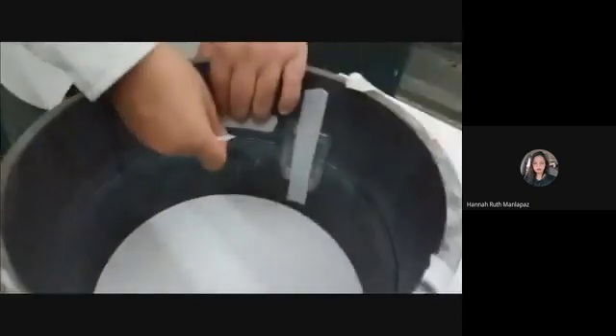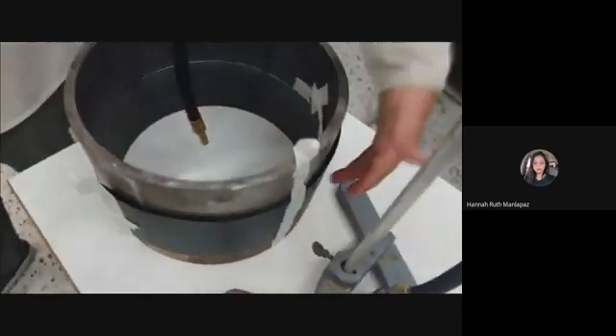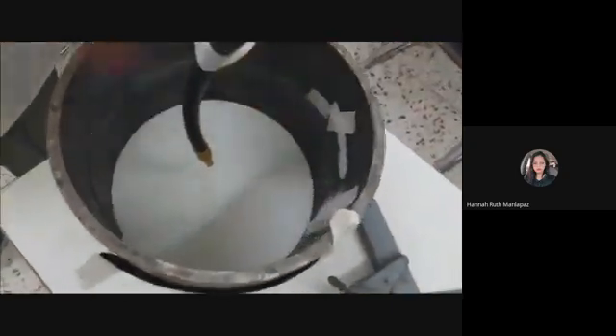Choose the appropriate IQI type according to the sample thickness of the same material as that of the specimen. IQI should be placed in a proper manner on specimen, i.e. source side and wires across the weld. Place the lead letters. Wrap the films around the welded pipe. Set the source at the center of the pipe using the magnetic stand. Calculate the exposure time by application. Process the films inside the darkroom.